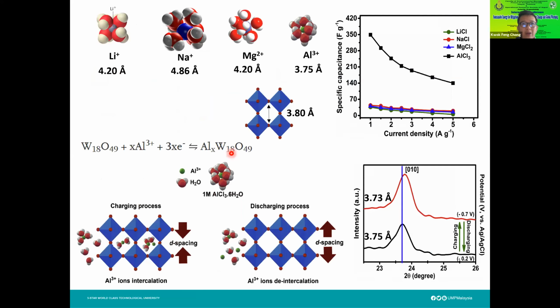Okay, then we try to explain it theoretically. We look at the hydrated cation sizes of the lithium, sodium, and magnesium, and then look at the crystal lattice spacing for the tungsten oxide. We found that it's in the range of 3.8 angstrom. For the aluminum ion, it's just nice, it can fit in. So in this case, for every layer of this tungsten oxide, the aluminum ion can go in and fit in. And because of this electronegativity, this aluminum ion can stay longer, and can get captured into this crystal structure.